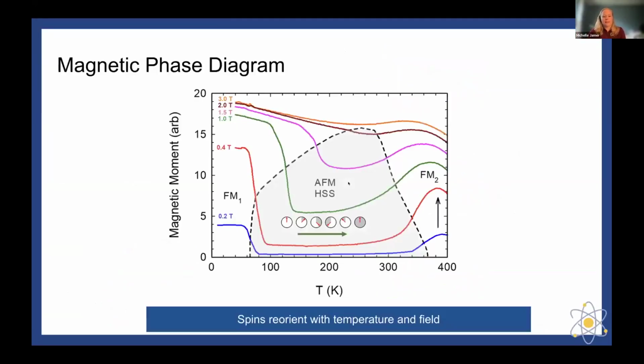So we can take a quick look at this magnetic phase diagram in order to see how the spins are oriented. At low field, low temperature, we have this first ferromagnetic phase. In this intermediate temperature, we have a helical spin spiral state, where it could be the helical spiral, the transverse conical spiral, or the longitudinal spiral. Whenever we get to high enough temperature, we introduce a secondary ferromagnetic phase, and we see that the spins reorient with temperature and field. And we have spent the last couple of years trying to understand what is the mechanism behind this.